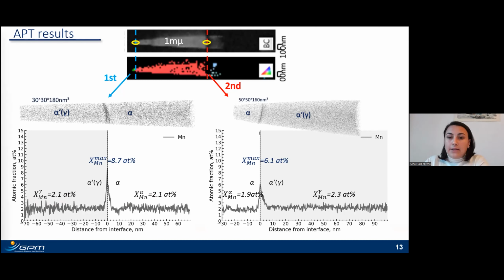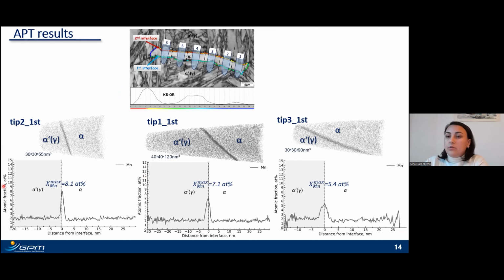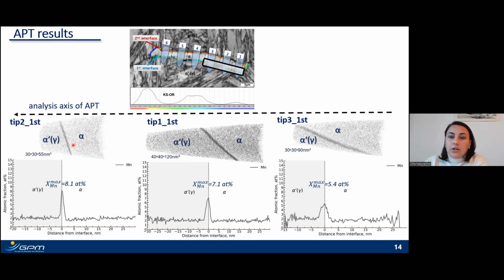But if you have a look at another example, where the composition profile is shown for the first tip across the first interface, we can see how the orientation of the measured interface with respect to the APT analysis axis affects the height and the width of the measured peak. So this presented result is a very nice example of why we cannot use the peak value as a quantitative measure of segregation. In addition to the observed issue, APT measurements can also be underestimated due to the well-known local magnification effect.